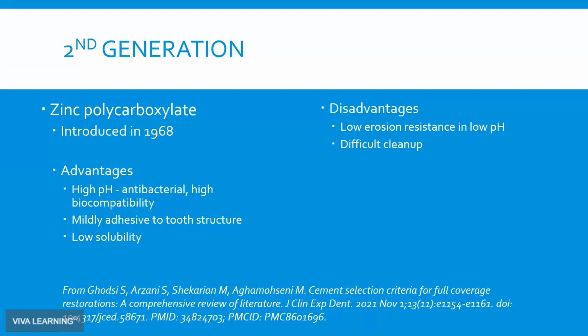The downside is it is a fairly tenacious cement, and to remove it required some modification of our protocol. But when it comes to resin, it's wonderful, because you remove a temporary with subgingival margins and there is not a whole lot of bleeding or inflammation and subsequent bleeding, I should say, which makes any bonding procedures that much more predictable, with less bleeding.